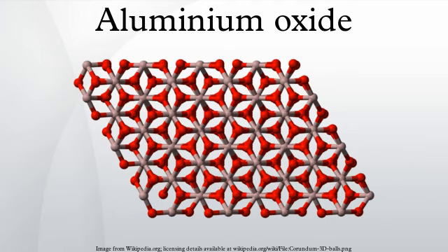Structure: the most common form of crystalline aluminium oxide is known as corundum, which is the thermodynamically stable form. The oxygen ions nearly form a hexagonal close-packed structure with aluminium ions filling 2/3 of the octahedral interstices. Each Al3+ center is octahedral. In terms of its crystallography, corundum adopts a trigonal Bravais lattice with a space group of R3c. The primitive cell contains 2 formula units of aluminium oxide.